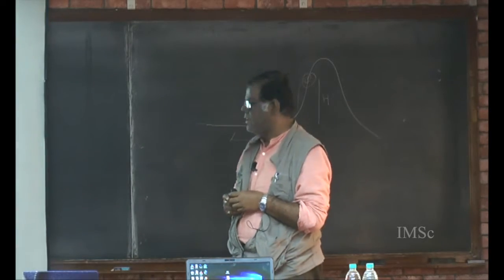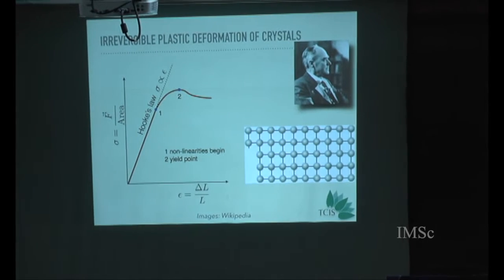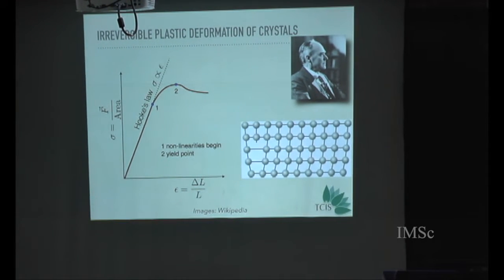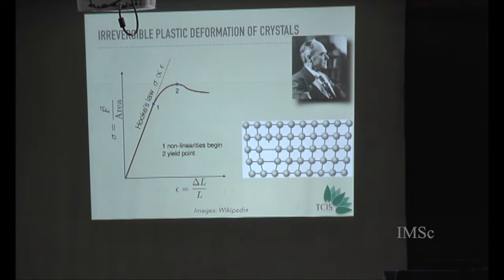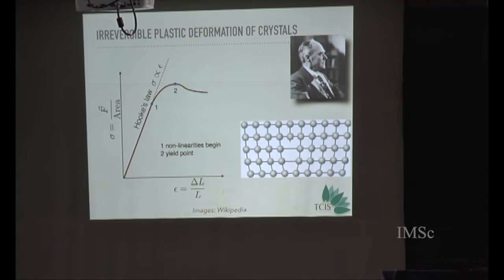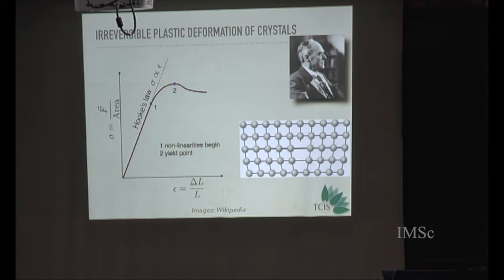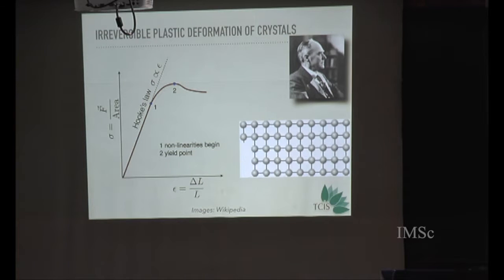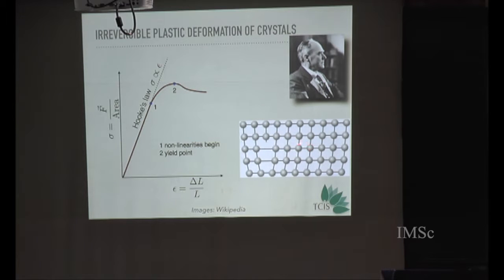So as you can see, if the crystal is not ideal and it has a defect like this, then the energy required is much lower, because you don't have to shift the entire layer. You can shift it part by part, and all the energy that you have to pay is to cut a few bonds and make new bonds in a very local region.